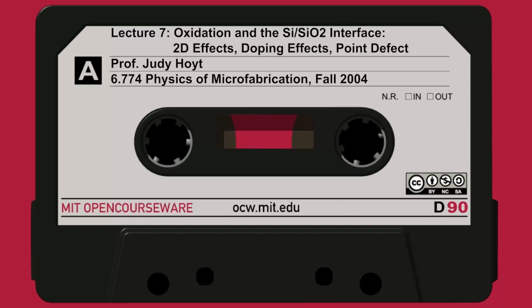And it's a side effect of, he believed, the stress effect, that there was stress buildup in the silicon and in the oxide in such a way that the oxidation rate would go down as the pillar got thinner and thinner. It ended up being somewhat self-limiting at a certain diameter pillar. It's not exactly the same kind of effect as in LOCOS, but it's related, and it gives you an idea that you can use these stress effects in processes to create structures that you wouldn't be able to otherwise create. If he didn't have this effect, he'd have a very good chance of really ending up with very few pillars that were of similar diameter.